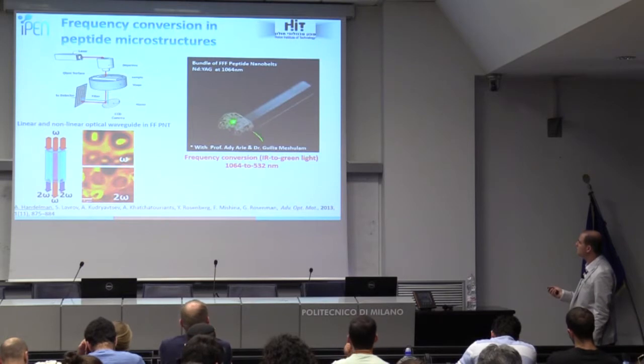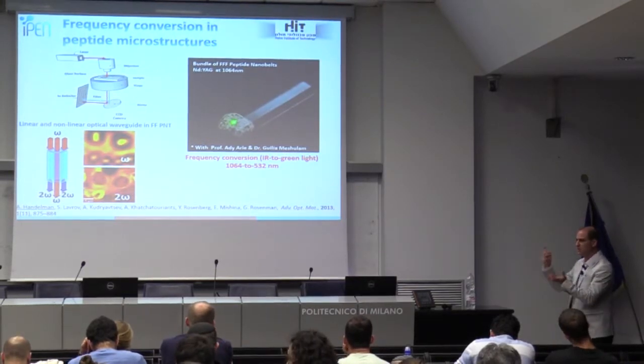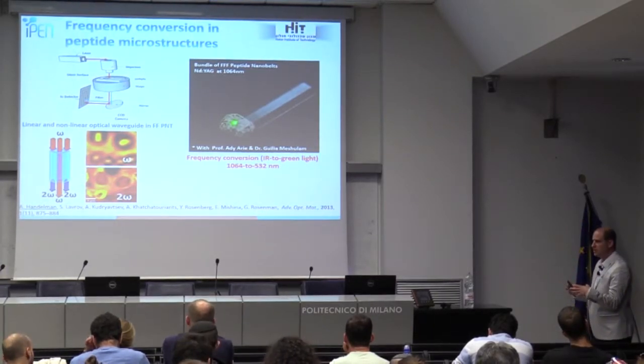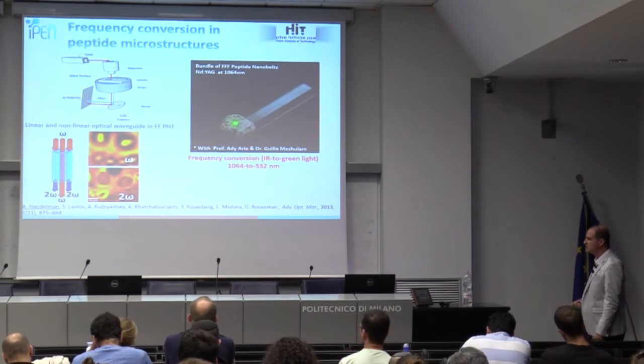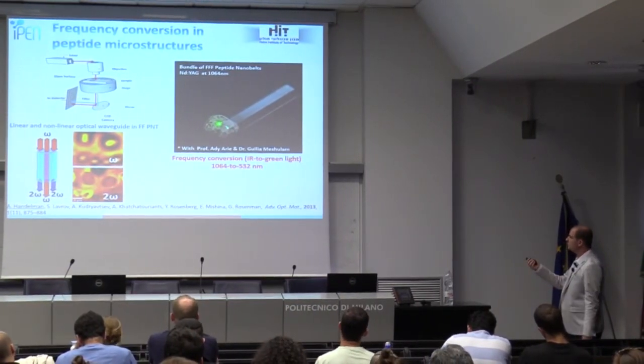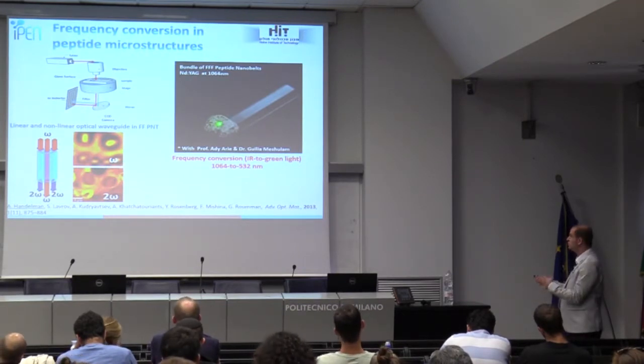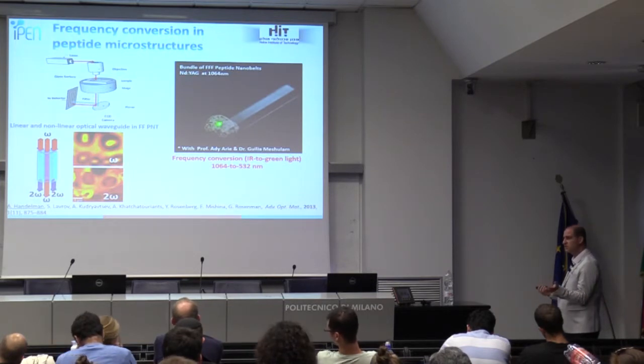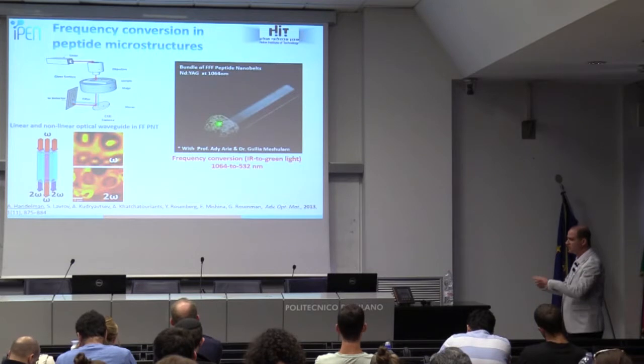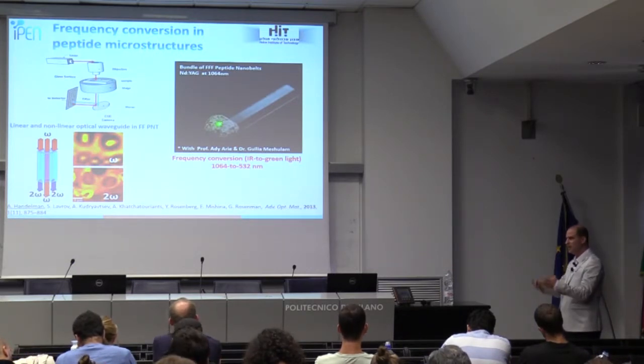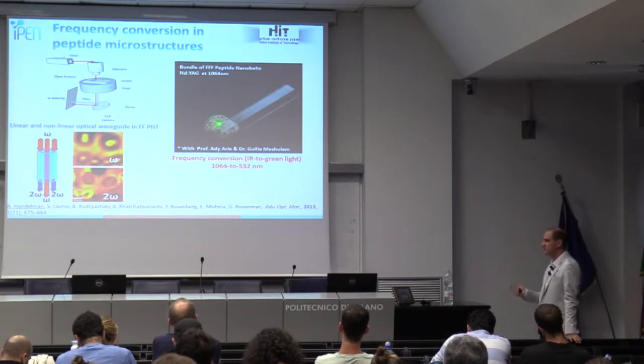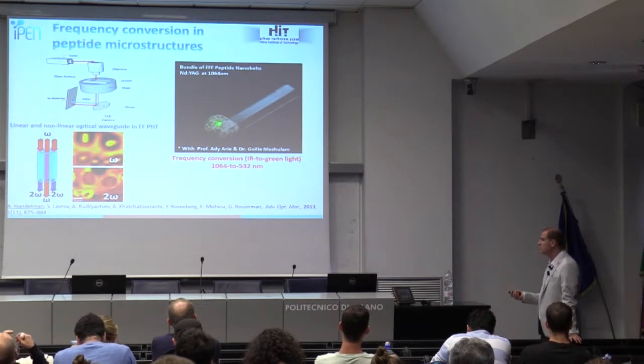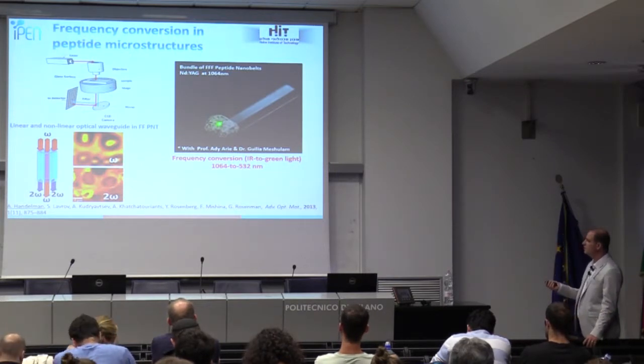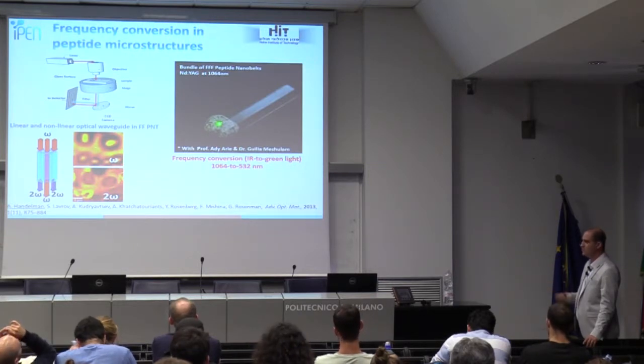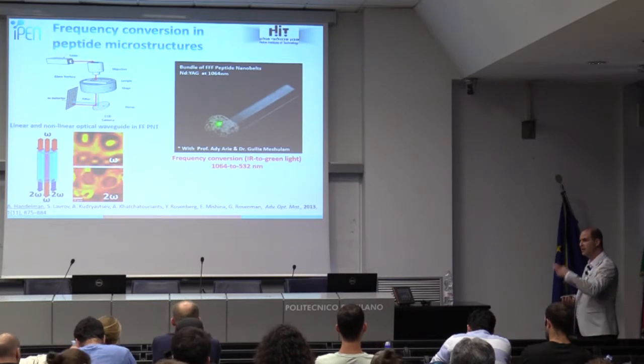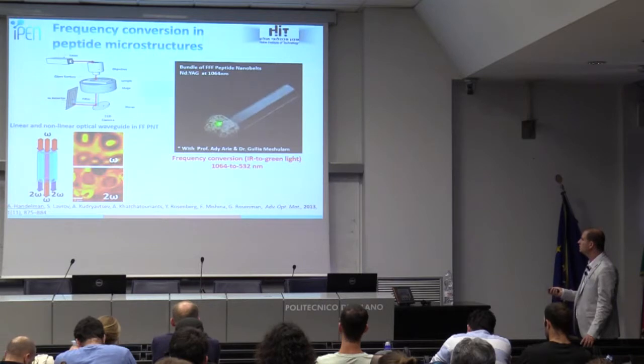And if we use, for example, a bundle of this kind of peptides, so we densify it and take a very large amount of peptides, we actually can see the second harmonic generation conversion. In the experiment you see here, we use an IR laser with 1064 nanometers, and this image was taken in a very dark room with a high-exposure camera, and we see here a very small green light, which means that there was a frequency conversion. We also show here nonlinear and linear waveguiding. The nonlinear waveguiding is only on the cladding of the tubes. All these kinds of applications.